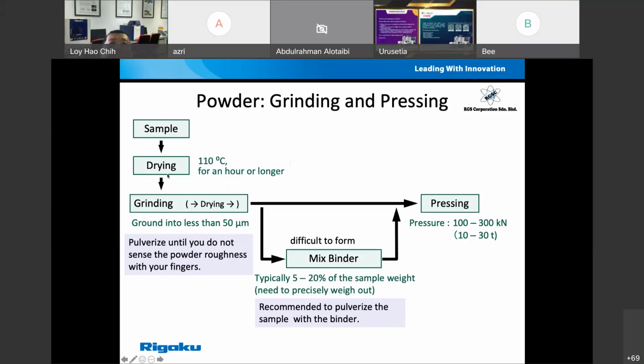Okay, so once the sample is dry, then you need to process by grinding. So grinding we recommend actually to reduce the grain size effects. So we need to control the grain size. Normally we recommend it to be less than 50 micron size. Okay, so after grinding, you have to feel that your powder sample is very smooth, something like you are feeling in your body talcum, your baby talcum, that kind of smoothness. Okay, this is for XRF.